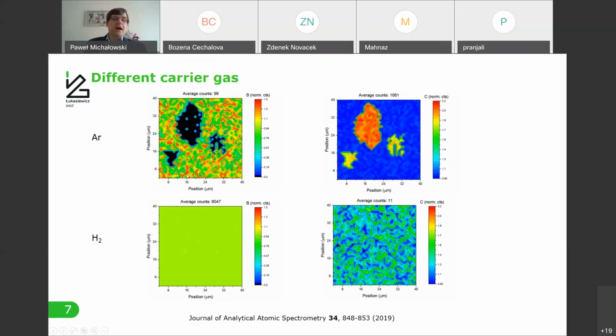On the other hand, for hydrogen, the very same material is very homogeneous, with very nicely distributed boron. When we switch to carbon analysis, we can see that there is a lot of carbon. I would like to emphasize that here the average counts for carbon dropped from 1000 to just 11 when we switch the carrier gas. And similarly, there were much higher boron counts for this sample than for this one.